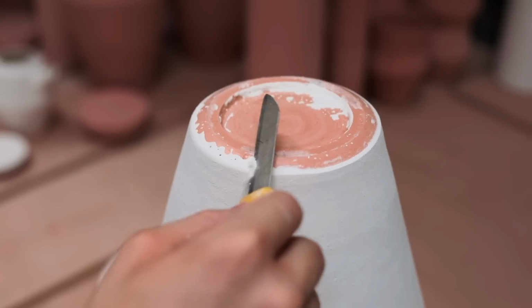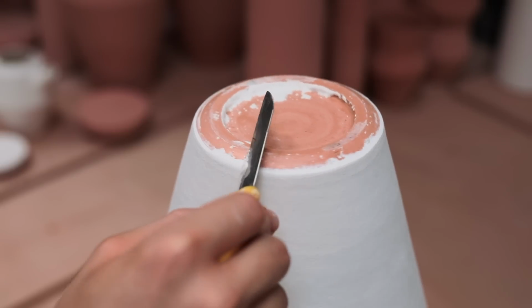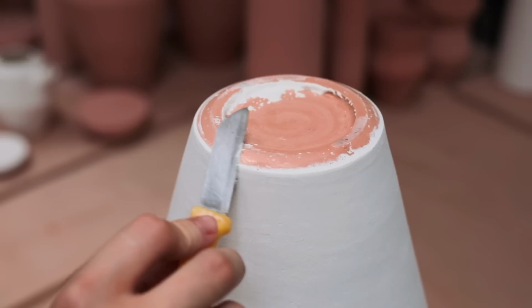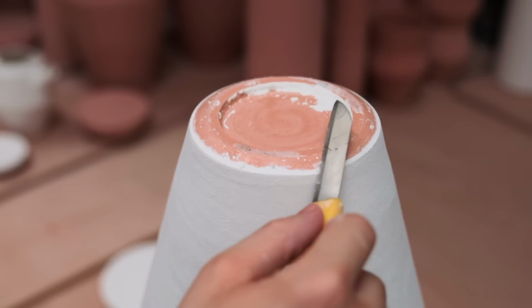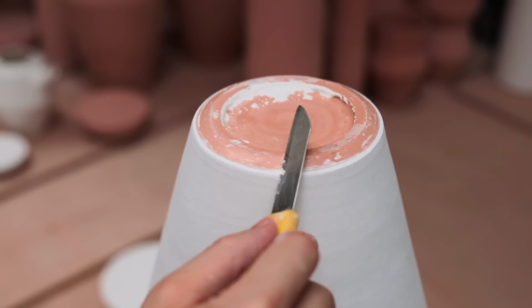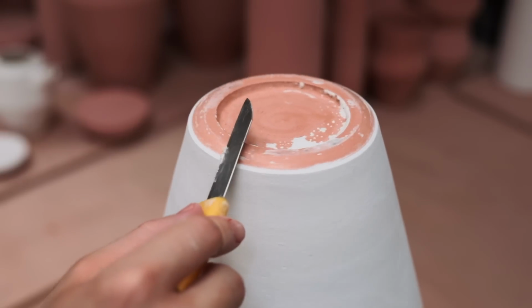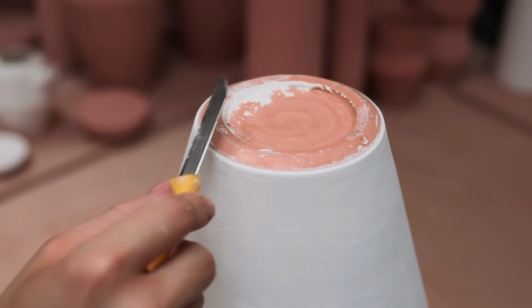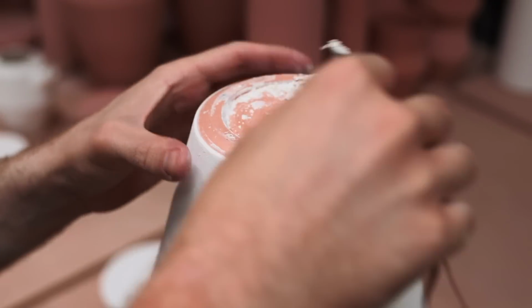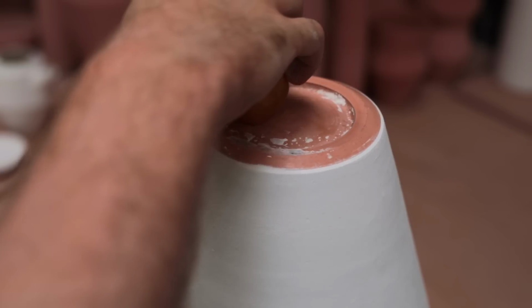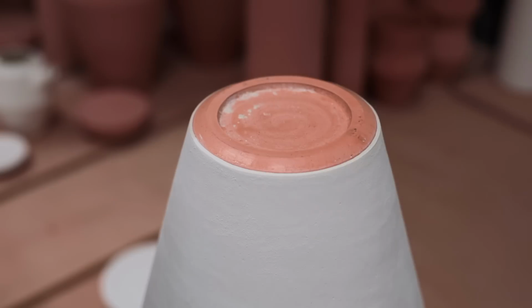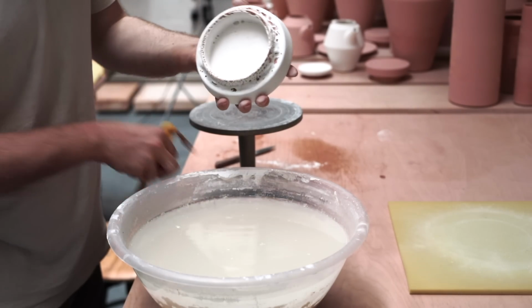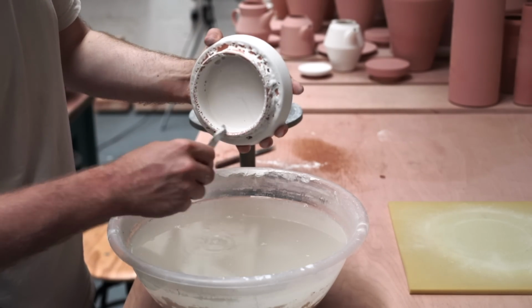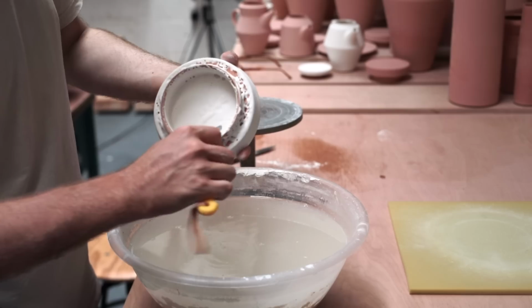The base is always the most important part to get right, and even though this piece was waxed, you can see just how much glaze ends up sticking to it, and all of it needs to go. As I beveled this outer edge, I can use it as a guide almost to slice a very even line through the glaze that encircles the bottom. Anything left inside the footwell is then gouged out, and then I go back over all of it with a wet sponge, so that it's as pristine as it can be, as if any glaze is left on this lower section, it could stick the pot to the kiln shelf when it's fired, potentially destroying the pot and damaging the expensive kiln furniture it's fired upon.